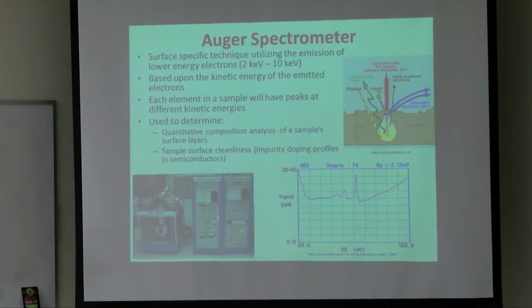You have Auger electrons, characteristic X-rays, photons, and backscattered electrons. Now, of course, this technique is just looking at this type of electron, whereas maybe the EDX we'll take a look at the secondary electrons. So this is also a surface type of technique. This is utilizing the emission of lower energy electrons, between 2 kiloelectron volts and 10 kiloelectron volts, whereas the EDX was a little bit higher than that.